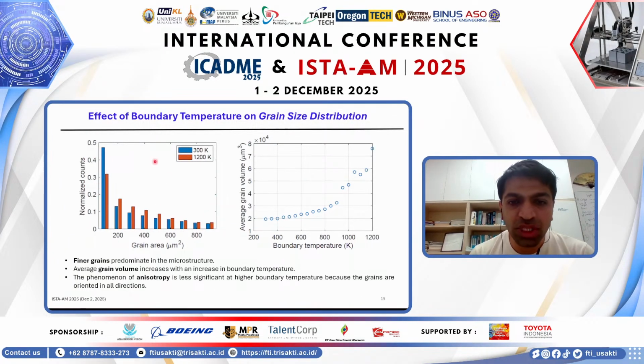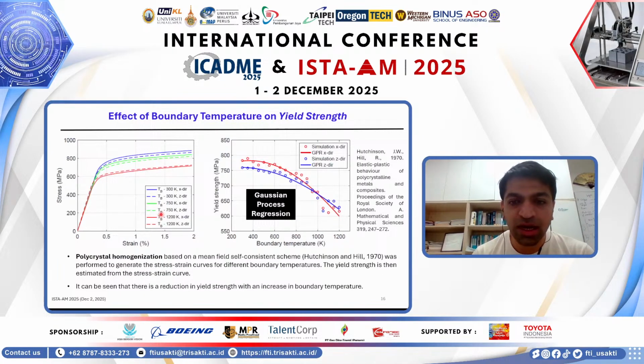And then we map all these grain structures into the statistical distributions. We look at the grain area distribution and the grain volume. And all of this then gets implemented in a homogenization model that helps us estimate the stress strain curves for different process parameter combinations. And from these stress strain curves, we finally estimate the yield strength. And this yield strength is the final performance metric that we care about.